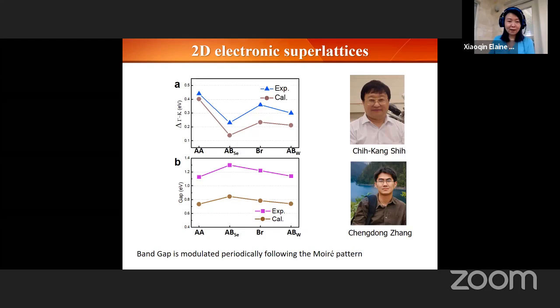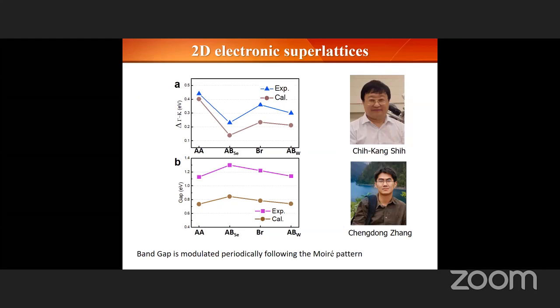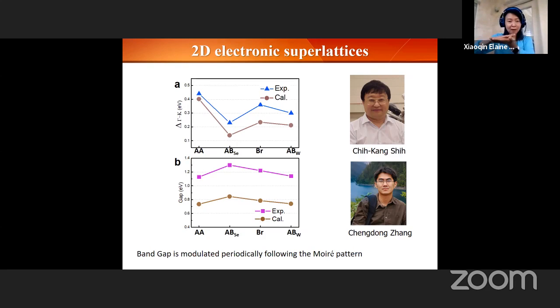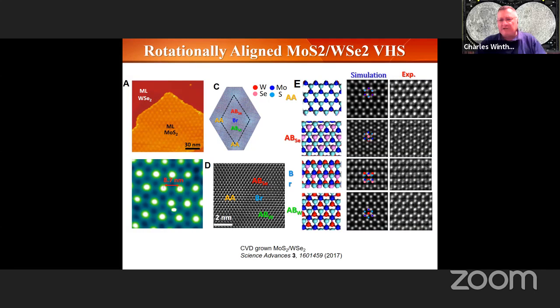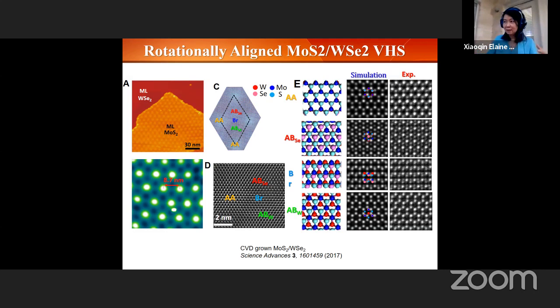The next thing is we went ahead and measured their optical spectrum, right? If I could just follow up on Bill's question, is it right to think of the exciton here as more or less like a free particle with some dispersion relation in the direction parallel to the planes, and then a radiative transition is a change in the relative binding of the electron? I think that is mostly correct if you have a monolayer, but now you have two layers, you also impose the lateral energy confinement. I see. Thank you. So they don't move freely in the two-dimensional plane anymore. I see, so there are sort of channels. Yeah, so now there's this checkerboard of energy modulation. And you're right, it's not like a square well, because the atomic alignment is gradually changing. But this picture doesn't always hold for all materials.